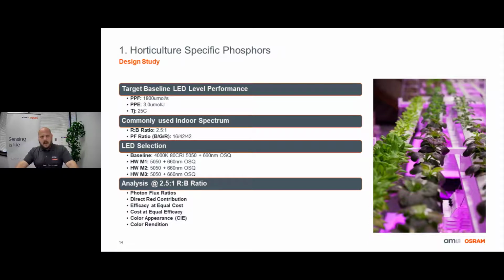For the spectrum, we analyzed and evaluated several different spectrums that are commonly being used for indoor applications. And we determined that for this, we would target a red-blue ratio of approximately 2.5 to 1 and have a photon flux ratio of 16% blue, 42% green, and 42% red. For the baseline, we used a combination of 4,000 Kelvin 80 CRI HortiCann S5050s in combination with 660 nanometer hyper red Oslon squares to match that red-blue ratio and that photon flux ratio.